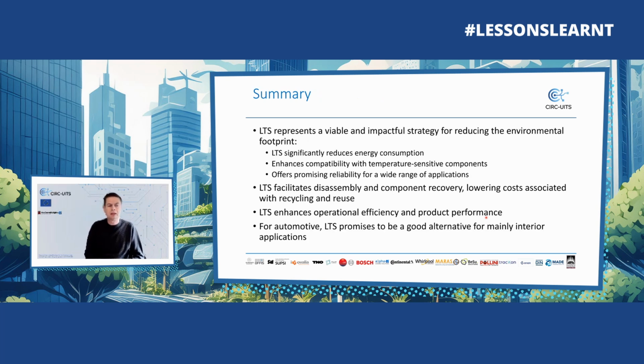So in summary, low temp solder represents a viable and impactful strategy to reduce the environmental footprint. It also facilitates disassembly, because if you use a lower temperature when desoldering components, it's less of a strain to the semiconductor, which we want to retrieve, which is also part of the Circ-uits consortium. For automotive, low temp can be a solution, but mainly for interior applications. As, like I explained before, some applications see elevated temperatures for which low temp solder is really not a solution.